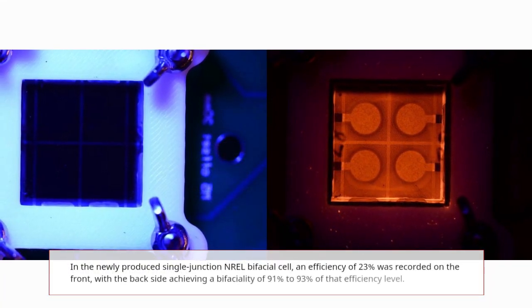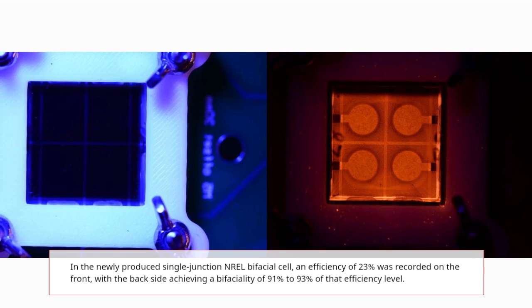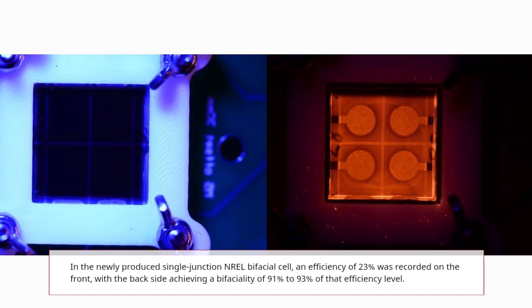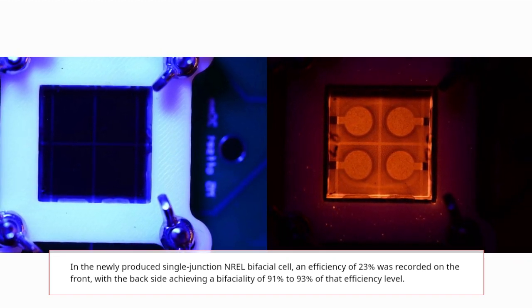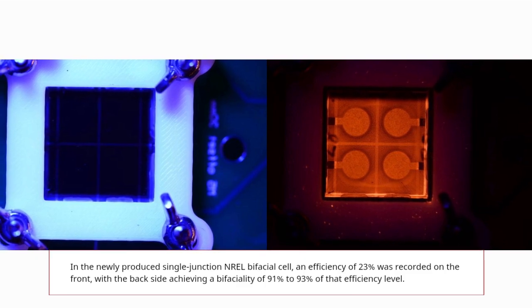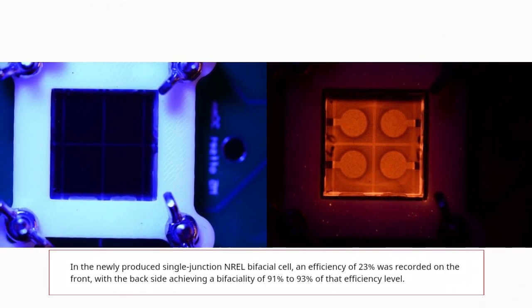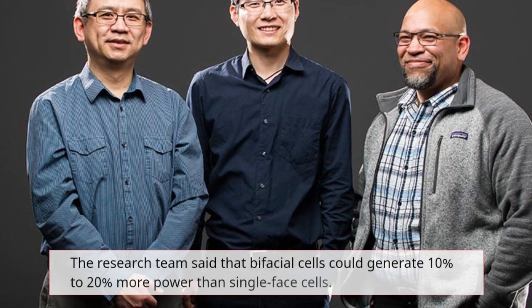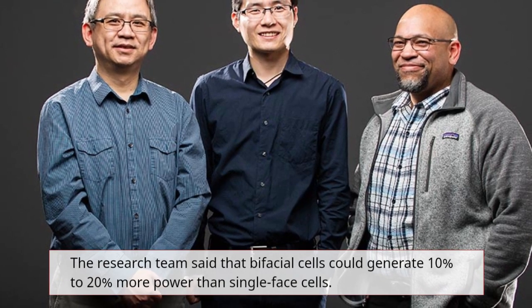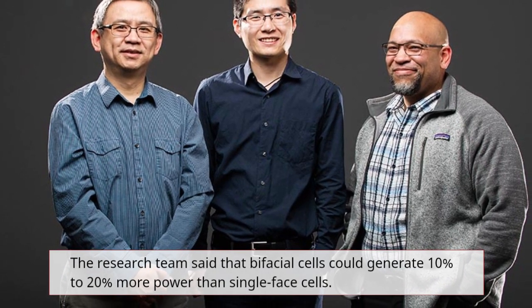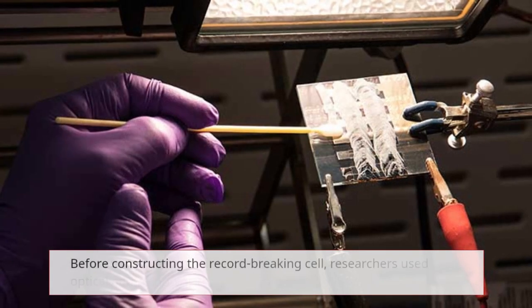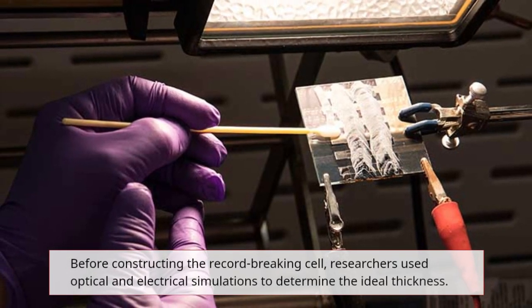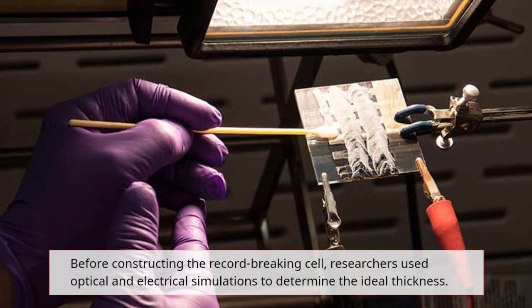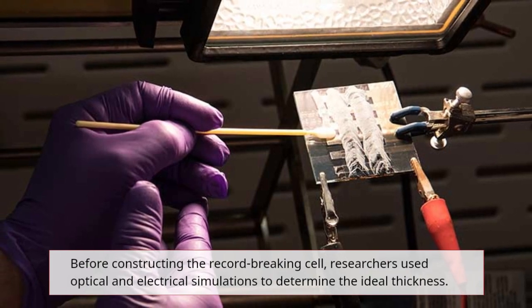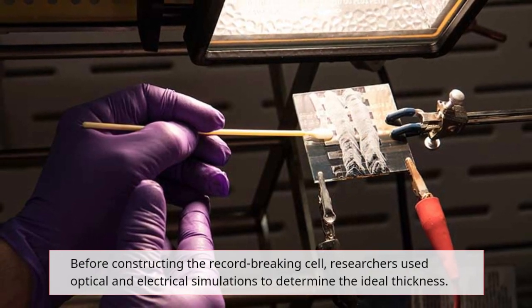In the newly produced single-junction NREL bifacial cell, an efficiency of 23% was recorded on the front, with the backside achieving a bifaciality of 91 to 93% of that efficiency level. The research team has said that bifacial cells could generate 10 to 20% more power than single-face cells. Before constructing the record-breaking cell, researchers used optical and electrical simulations to determine the ideal thickness.